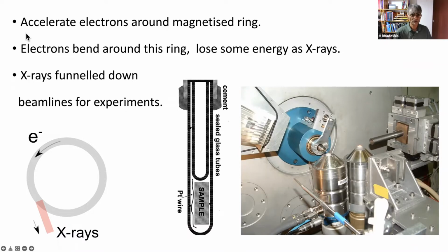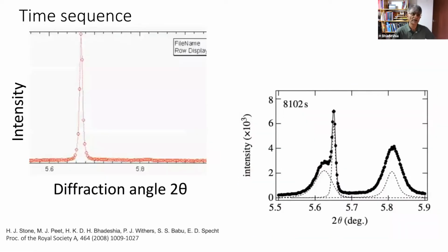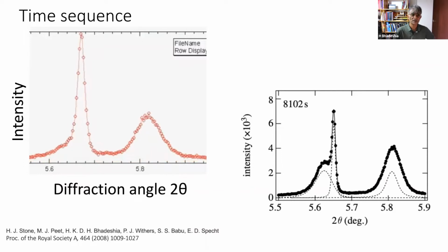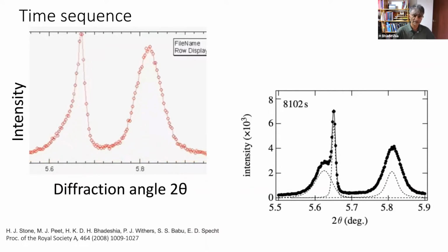And synchrotrons basically work by accelerating electrons around a magnetized ring. The electrons bend, and in doing so, they lose some energy as X-rays, and these are funneled down various beam lines located around the synchrotron. So we did this experiment, and the great thing is that you can collect diffraction data as a function of time with a high resolution.